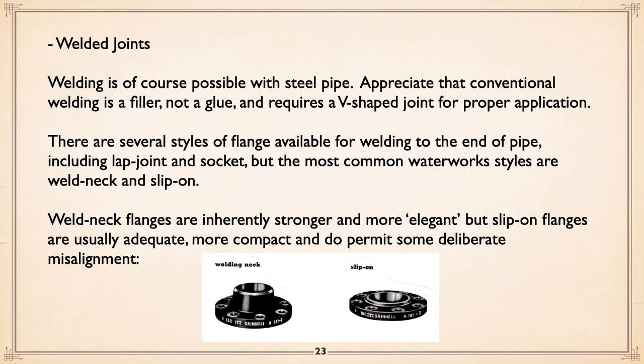Welded joints. Welding, of course, is possible with steel pipe. That's a big thing with it. Appreciate conventional welding as a filler, not a glue, and you should have a V-shaped joint for proper application. You can actually get rings with little spacers that you would put between two ends of pipe, and basically that's used as a bit of a filler when you weld the thing and make sure you've got the proper separation. So the joints have to be V-shaped. There's a bit of a trick to do it properly. And if you notice, the fittings will allow for that, an angle joint.